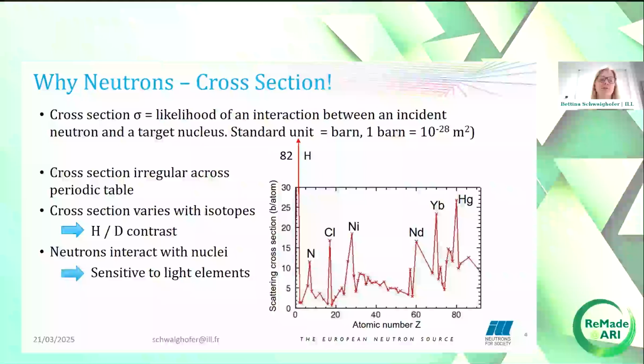Another great advantage or specialty of neutrons is their cross-section. The cross-section sigma is the likelihood of an interaction between an incident neutron and a target nucleus. This cross-section, as opposed to the interaction with X-rays, varies randomly across the periodic table. This means that we can sometimes distinguish neighboring nuclei very well, and we can probe light elements in the presence of heavier elements. For example, neutrons are especially sensitive to hydrogen, and the cross-section also varies with isotopes, which allows us to use hydrogen and deuterium to create contrast, highlight or hide particular features of a structure.